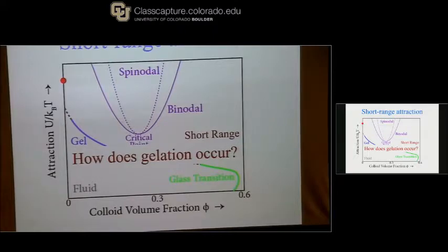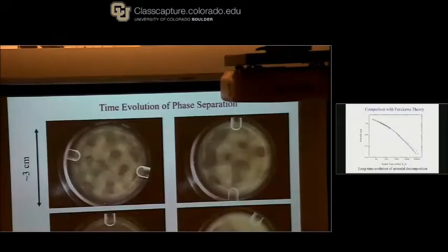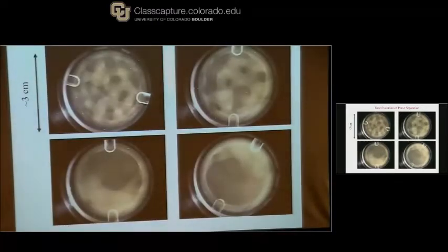Short-range interaction is where, okay, here, this one, you do clearly get a phase-separated region where essentially you get a gel. There's a solid connecting region of colloid-rich region that spans space. But the colloids are not really touching one another, or they're not very strongly interacting because the interaction energy is so weak. They're interacting, they're attractive, but they're not really solidly touching.